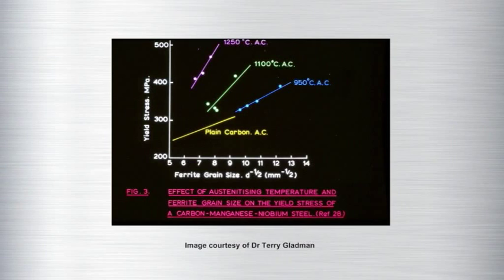But this only happened in the normalized condition or after very low temperature rolling. If you used high solution temperatures, as you do with hot rolling, then in the as hot rolled condition, the niobium steels were substantially stronger than they would have been according to the grain size and other factors. Now, this extra strength of niobium was due to precipitation strengthening.